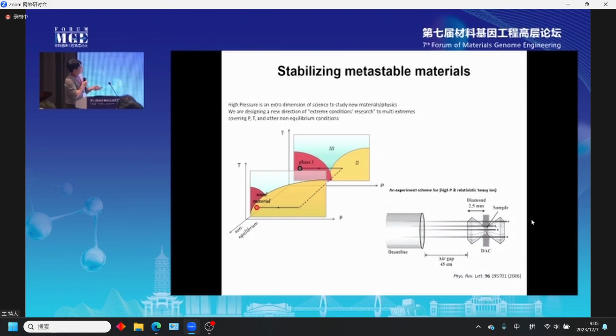This is a very schematic idea. If you pressurize a material, and put some beam on it so that high irradiation happens, then in this sample, this is an equilibrium phase diagram, for example, and if you apply a non-equilibrium path like high irradiation or some very rapid dynamics, then this phase diagram can be much distorted. Once we recover this high pressure material back to ambient, maybe we can stabilize this material at ambient conditions. So this is a non-equilibrium path. We try to find new materials which exist only at high pressure, but which can be recovered back to ambient conditions.